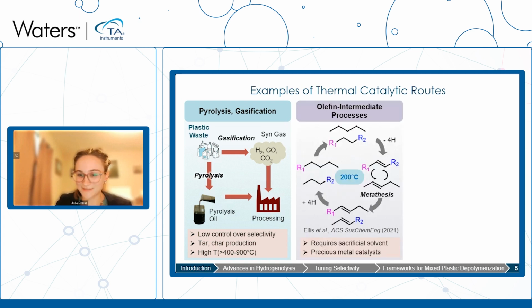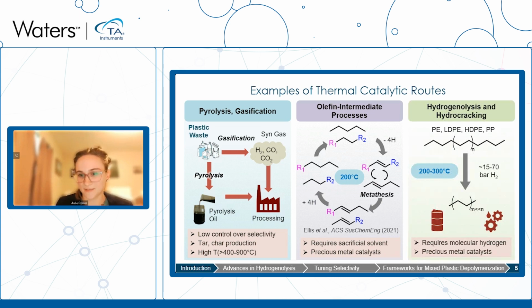I won't go into a ton of detail about these since I believe you'll hear about them more in the next talk. But these are really exciting processes because they don't require molecular hydrogen to break apart carbon-carbon bonds, but they do require a sacrificial solvent and often require precious metal catalysts as well. What I'm going to be talking about today is the reductive routes of breaking apart polyolefins, including hydrogenolysis and hydrocracking, where you can take polyethylene and polypropylene at low temperatures, 200 to 300 degrees C, using hydrogen and break them apart into different products. This does require molecular hydrogen and precious metal catalysts, but hopefully I'll show you why these are some pretty exciting reactions.